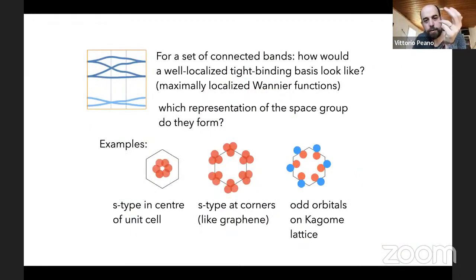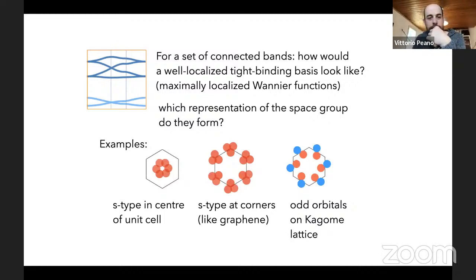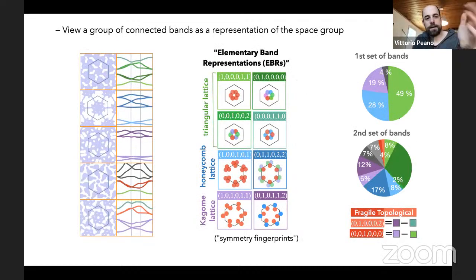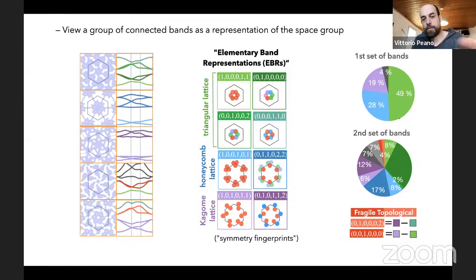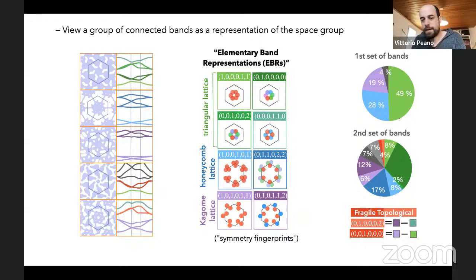This is very powerful: for a fixed space group, all bands with an atomic limit can be viewed as built from simple building blocks — band representations — and for each building block one can predict the symmetry labels. We use our neural network, which predicts band structures and symmetry labels, to identify bands incompatible with band representations, i.e., topological bands such as fragile topological bands.